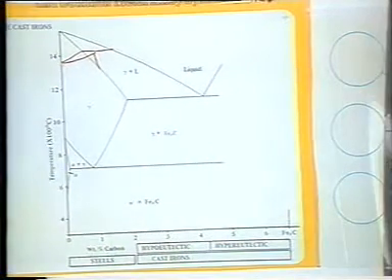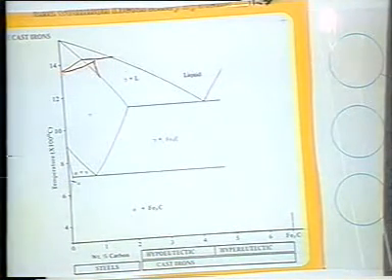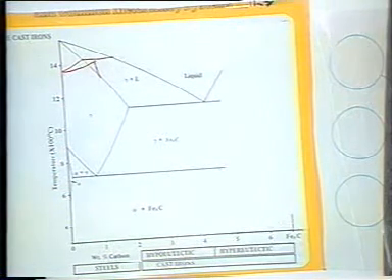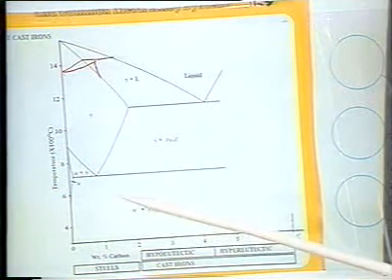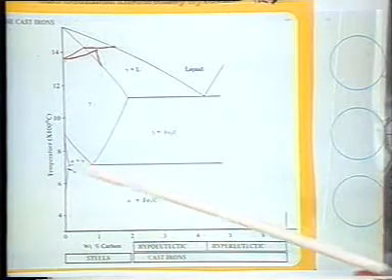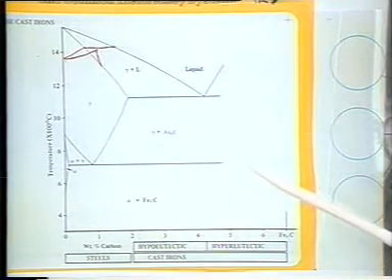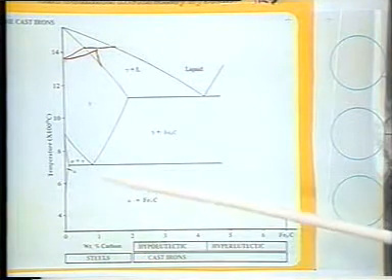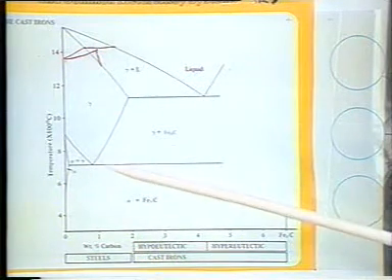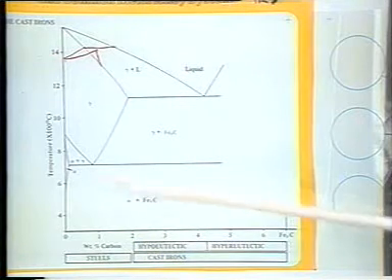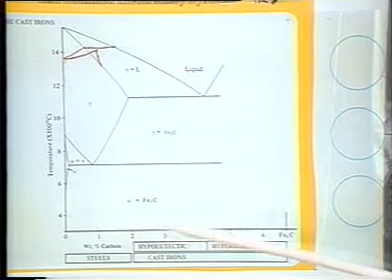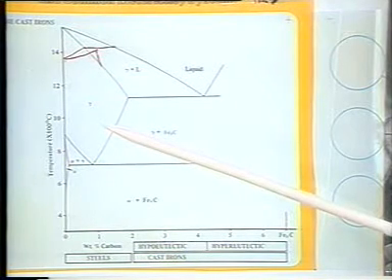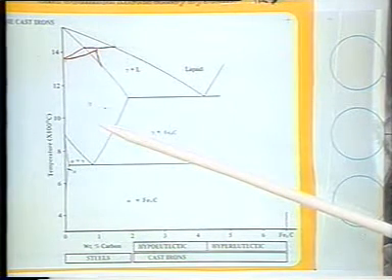Well, if you can remember the diagram now, just visualize when I talk about 1333 degrees that I am really talking about this temperature that exists right here. This is the eutectoid temperature. That is the allotropic transformation of iron for a material that's about 0.85% carbon. Then I'm always talking about going from this material, which is a mixture of alpha plus Fe3C, to this material, which is going to be just pure austenite, single phase.